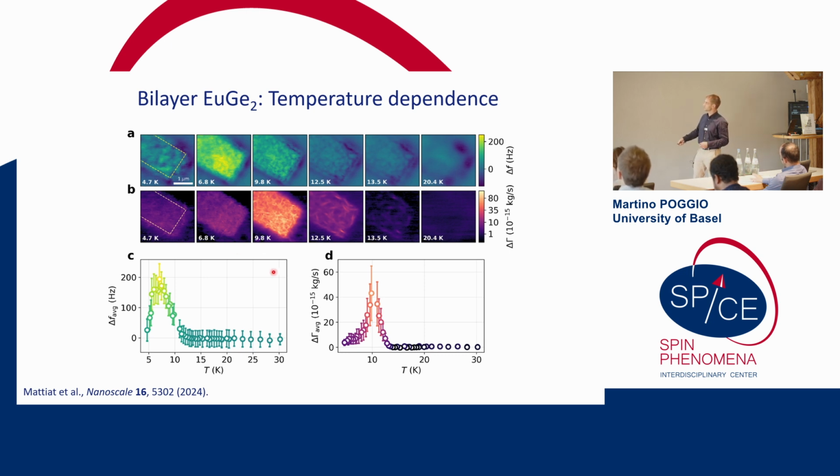And then, of course, it makes a lot of sense that these signals are peaked near the magnetic phase transition. What you can also see from these images is very fine structures here on the order of 100 nanometers or so, and we think that this has to do with this phase separation, so that this indicates domains of ferromagnetic and antiferromagnetic phase, because they should have different response in the susceptibility. Unfortunately, this is just some evidence. We would need to do quite a bit more experiments to put this on solid ground, but very unfortunately, these samples came from Russian collaborators, and we couldn't continue this collaboration anymore for reasons beyond our control.